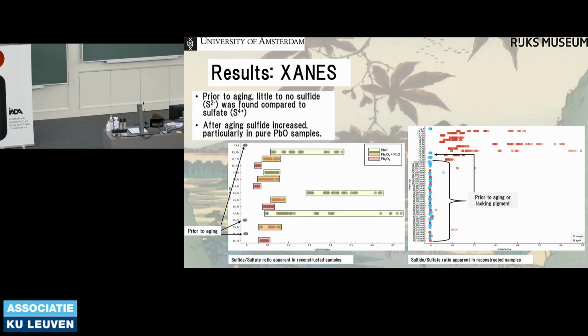Specifically, it was found that prior to aging, there was very little sulfide compared to sulfate, and after aging, this ratio increased significantly. In particular, in the pure lead monoxide samples, this increase was observed the most, which is logical considering that during the printing process, it was found that the more lead monoxide was added to a sample, the darker and more discolored the samples became.